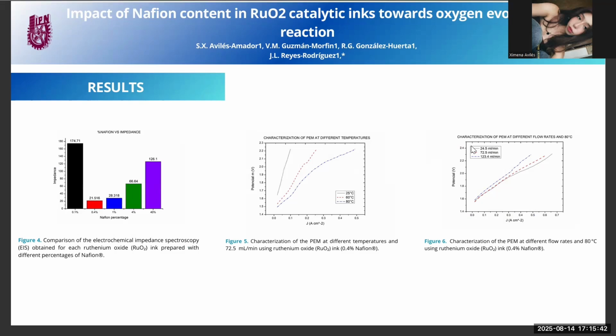Best preliminary performance was observed at 72.5 milliliters per minute at 80 degrees Celsius. The study also identified 1% NAFION as a promising alternative, and both will be analyzed further for long-term stability.